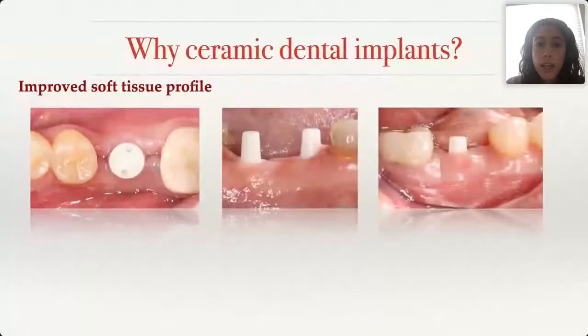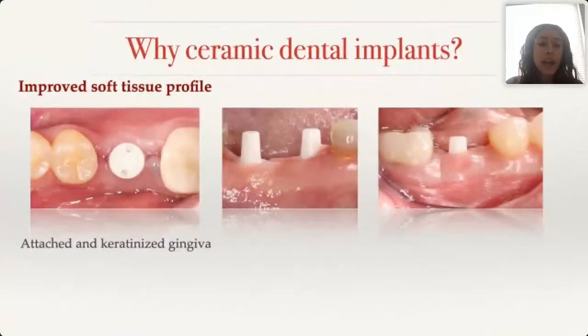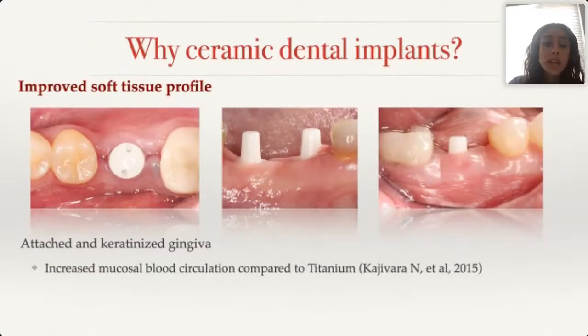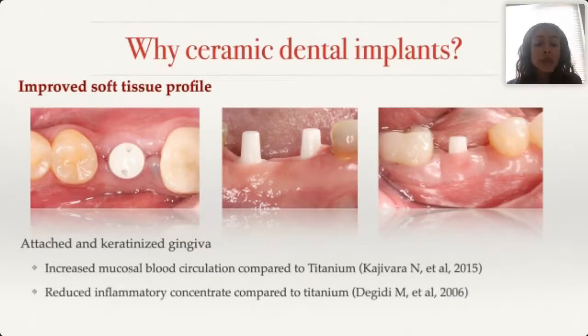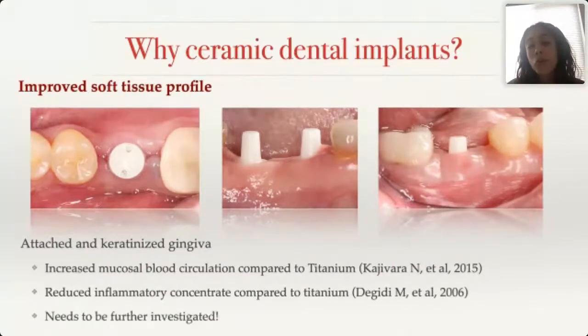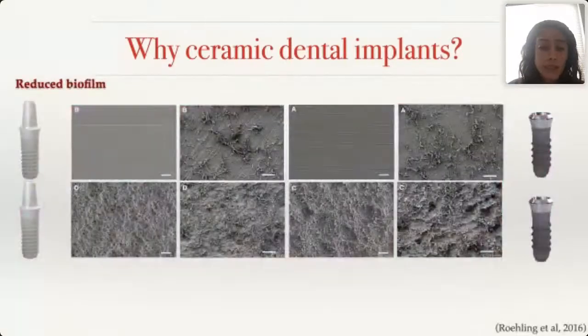Another reason that I think these implants have an advantage is the improved soft tissue profile. We get very nice attached and keratinized tissue around the abutments and the implants. The tissue sometimes even moves coronally, so we have to really uncover the implants and remove tissue. But overall we get nice attached and keratinized gingiva. We don't know scientifically why this happens, but there are studies that have shown increased mucosal blood circulation around zirconia compared to titanium, and reduced inflammatory concentrate around zirconia compared to titanium. But we need further investigation to know why we see this nice result.